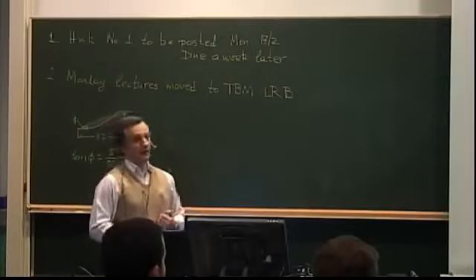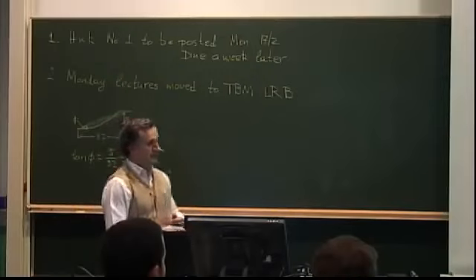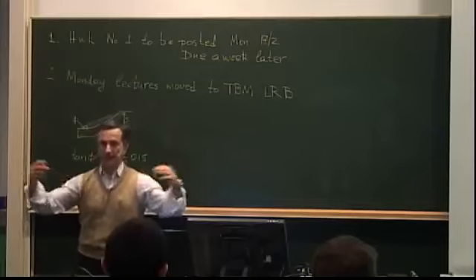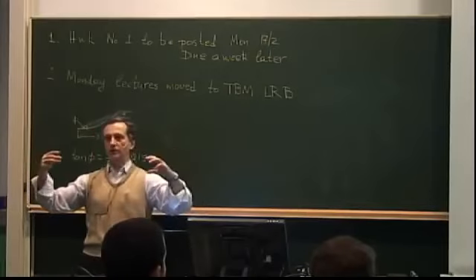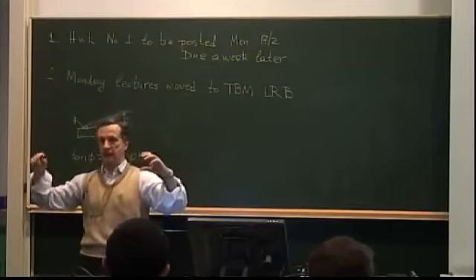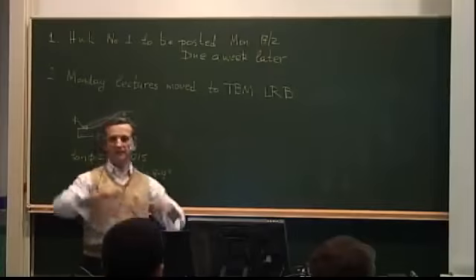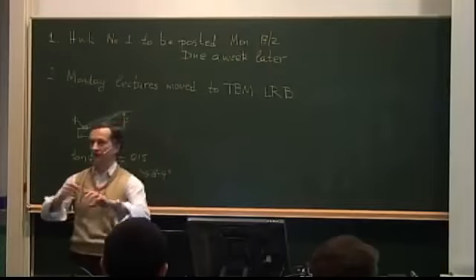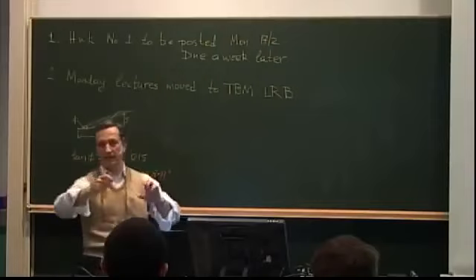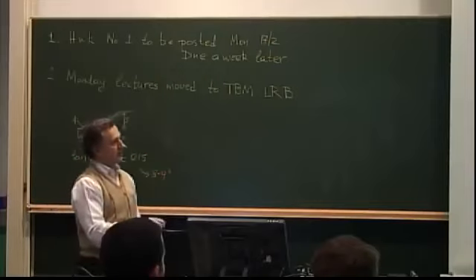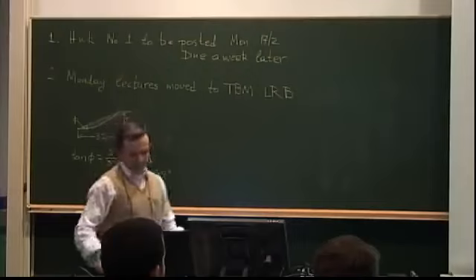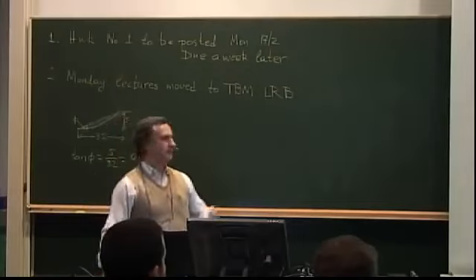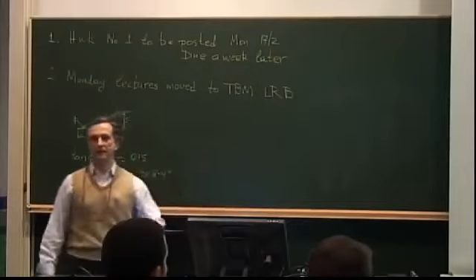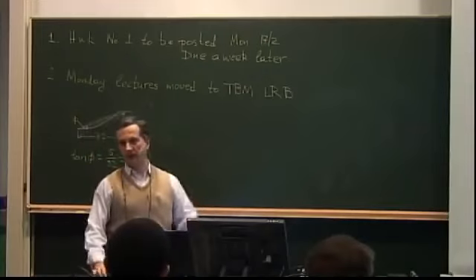Now, applying compression in these means that the waviness will increase. Basically, the fibers try to shorten, but because they are already bending out of shape, they will bend more. As they bend more, they develop higher bending stresses. So the combination between the compression stress and the bending stress will eventually cause this to fail. Well, we admit defeat until my student finishes his work, then maybe we can have better results.